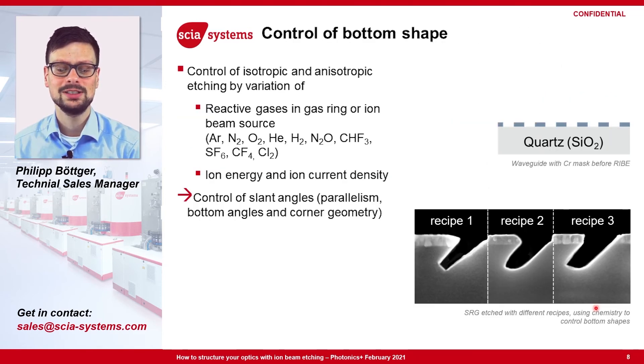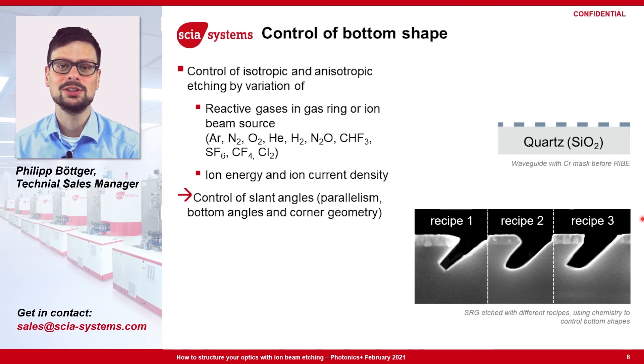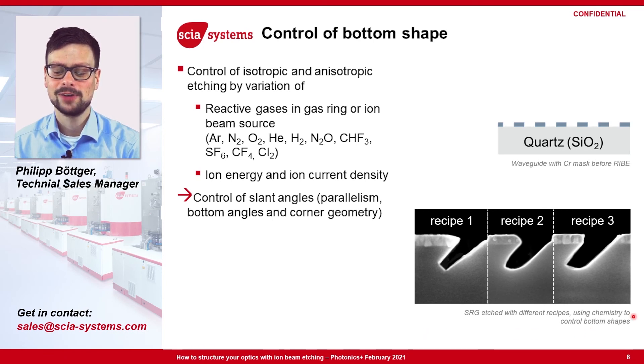But not only the angle of incidence is important to reach a good result — other process parameters are also very important. For example, you can change ion energy, beam current density, and again gas composition by using reactive gases. With this you can change the ratio between isotropic etching and anisotropic etching, and therefore gas composition can have a huge effect on the final shape of your gratings.